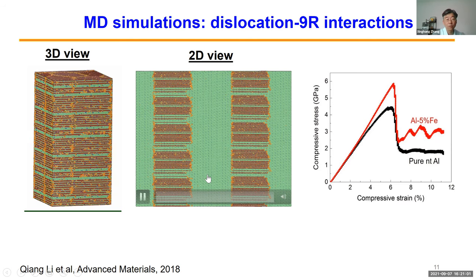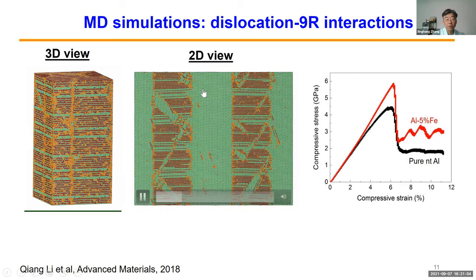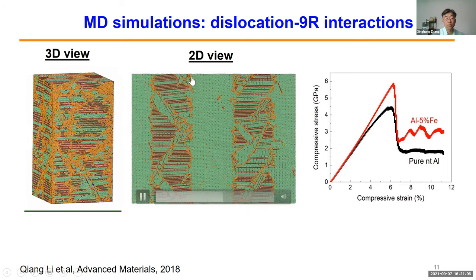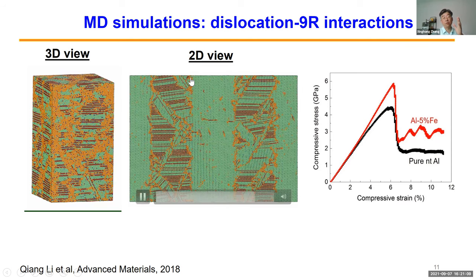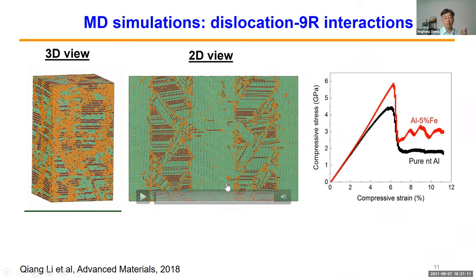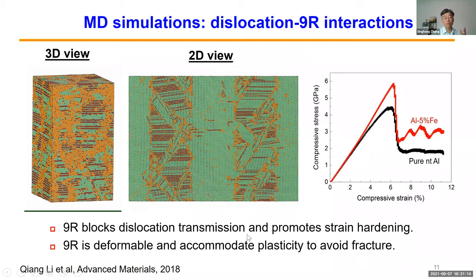If you do this kind of compression test, you find the 9R actually acts as walls to block dislocation penetration. That gives us a couple of impacts. One is that they block dislocation transmission and give you strain hardening. So this is the stress-strain curve for aluminum iron. You see very high strains and strain hardening. On the other hand, if these walls remain rigid, you would reach a very high stress level, and eventually the whole thing might fracture. But that's not the case.